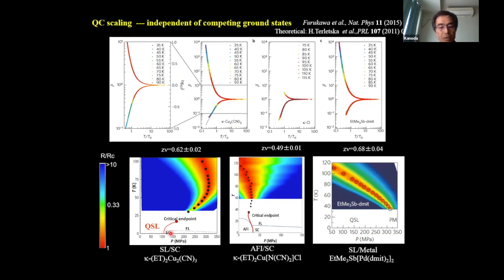The 3 materials, each of which have different ground states. This material has a spin liquid Mott insulator and superconducting phase in the metallic side. But this material is an antiferromagnetic Mott insulator and superconducting phase. And this material is a spin liquid Mott insulator and normal metal in the metallic side. So the ground states are different for these 3 materials. However, we examined the transport. We measured the transport.